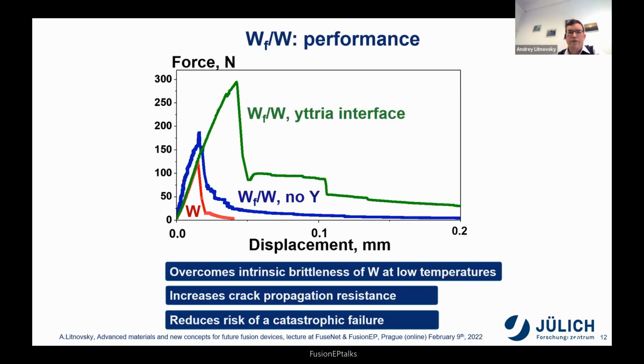To see it with numbers, if you apply the force and look at the displacement, the pure tungsten is shown here. You see that with applied force it simply breaks, so there is no displacement, it basically gives up. Whereas even for the first non-optimized design, you see that after the first initial crack, you can still tease the material, so it can still expand and go further.